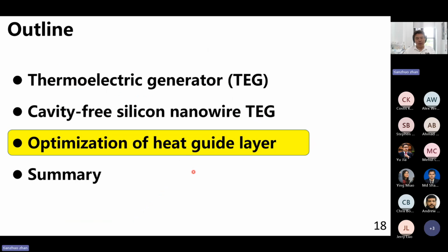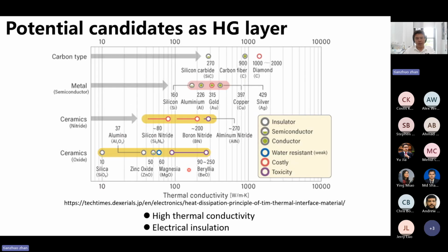And so next I will show you how to optimize the heat guide layer to decrease the parasitic thermal resistance. So the heat guide layer should be thermally conductive and also electrically insulative, and so this table shows the materials with different thermal conductivity and also electrical conductivity. And we know diamond has the highest thermal conductivity, but it's very difficult to form high quality diamond thin films at low temperature, and typically we need to use a temperature of more than 1000 degrees to form high quality diamond thin films.